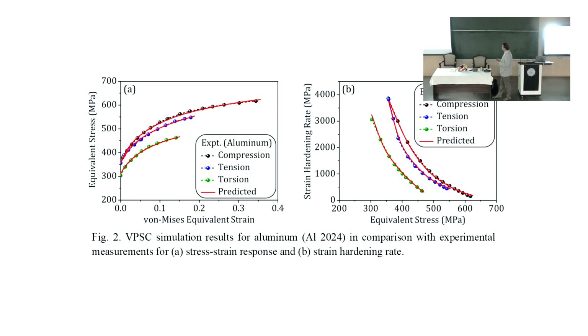So here you see for an aluminium 2024 in different tensile, torsion and compression testing. This is the rate of hardening, the experimental derivative of the stress strain curve, the strain hardening rate. This also compares very well between simulation and experiment.